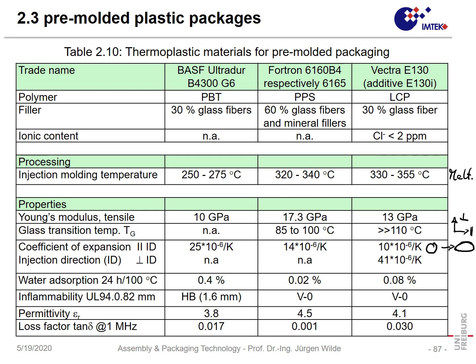So that means making parts from such LCP material is not so simple, because you want to have a cube, let's say 1 centimeter in each direction, and in one direction it is 20 micrometers smaller than in the other direction. That would mean you have to rework your mold. Of course, the mold can always only be made larger, so you must first make one which is too small, then you measure it, you rework your mold, you do the molding process again, and so on, and that is quite time consuming. So that's the reason why injection molding is a very good process for mass production, but the initial costs or the general costs of having that process and operating it are very high.